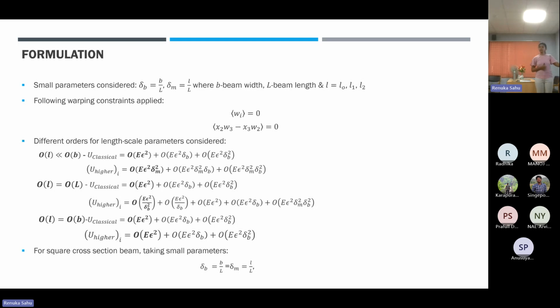In another case, the length scale parameter is taken equal to the beam length. Here the higher order energies have lower order compared to the classical strain energy. For the third case, where the material length scale parameter order equals the beam width, the classical strain energy and the gradient higher order strain energies come to be of the same order.